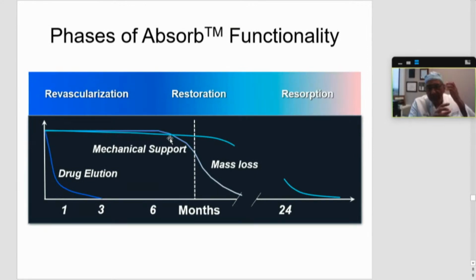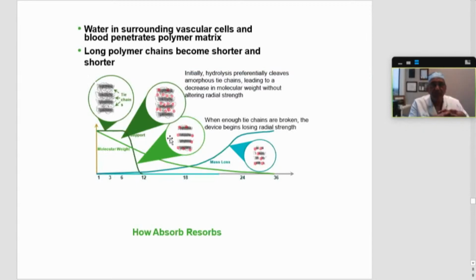So how does a bioabsorbable stent work? This slide is specific to the BVS Absorb, but you potentially can use this for all bioabsorbable stents. The first phase is the revascularization phase, where there's drug elution in Absorb. It elutes everolimus up to 3 months. And then the second phase is restoration, where you have gradual loss of mechanical support, and there's restoration of the vessel. And then eventually there is mass loss, and there's complete resorption of the bioabsorbable material, PLLA. That happens in about 2 years.